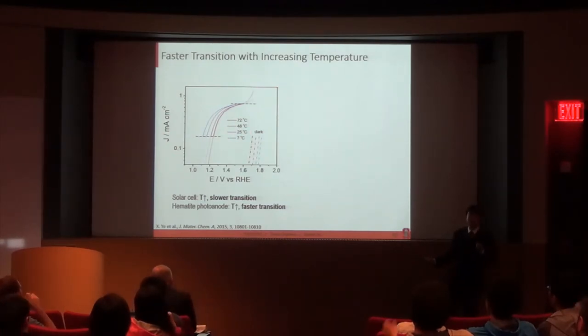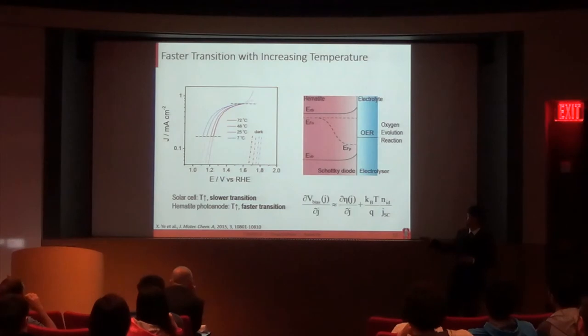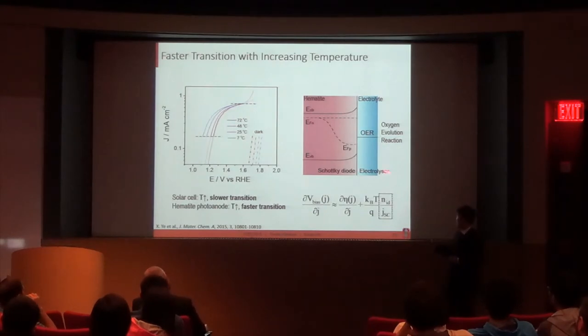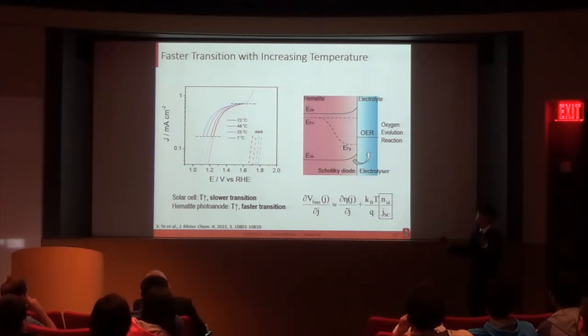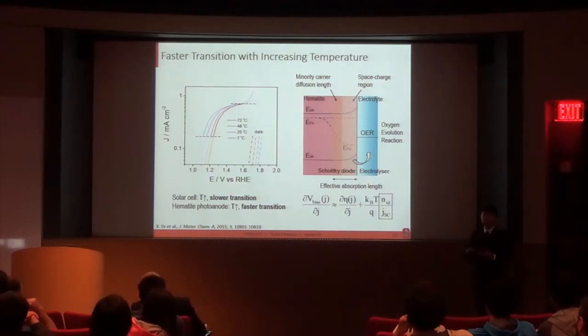Such a faster transition is actually quite different from solar cells, where typically a slower transition is associated with higher temperatures. To understand this behavior, I modeled this hematite photo anode with a Schottky junction diode in series with the electrolyzer, with a shared interface. I fitted this JV characteristic with an ideality factor and a short circuit current. The ideality factor describes the recombination and the charge transfer properties at this hematite interface, while the short circuit current describes ideally how many carriers you can collect from this hematite. That includes the carriers generated in the space charge region, plus the carriers that are beyond the space charge region but within the minority carrier diffusion length. That is the effective absorption length in hematite.